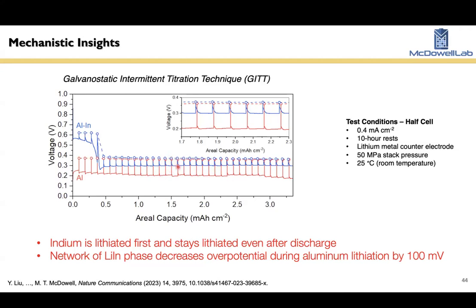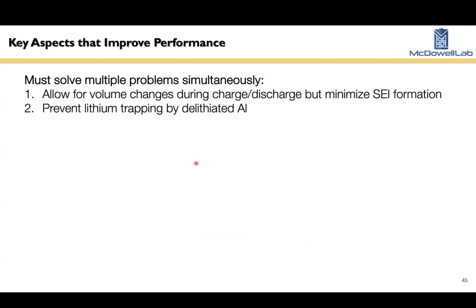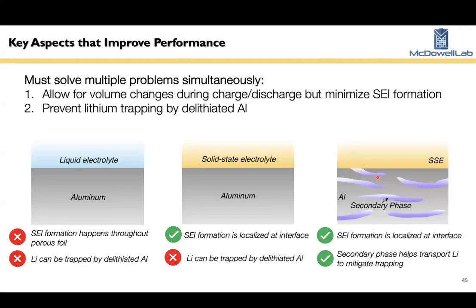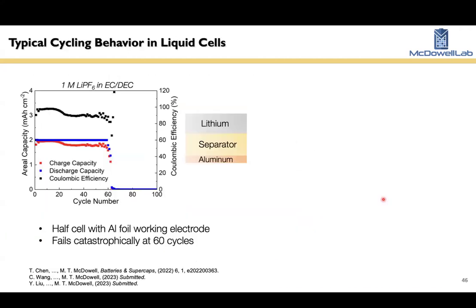And this is, we think, because there's better transport of lithium, and there's a 3D network of the indium within the structure that allows for a lower overpotential during the aluminum reaction. So this is very useful for improving kinetics. Overall, the distribution of the secondary lithium indium phase within the structure is very useful for improving kinetics, improving coulomb efficiency, and improving cyclability. And we think that this idea of microstructural engineering of anodes can be very useful, even working towards commercialization for solid state batteries.